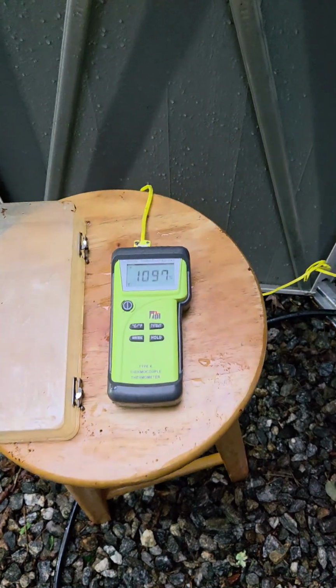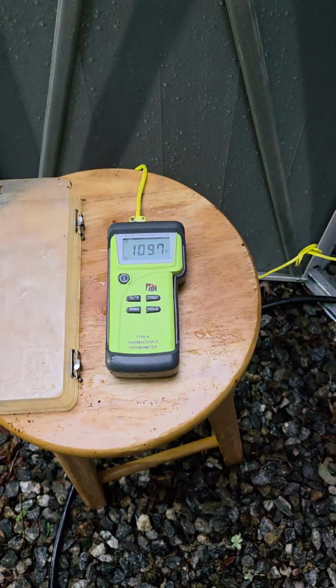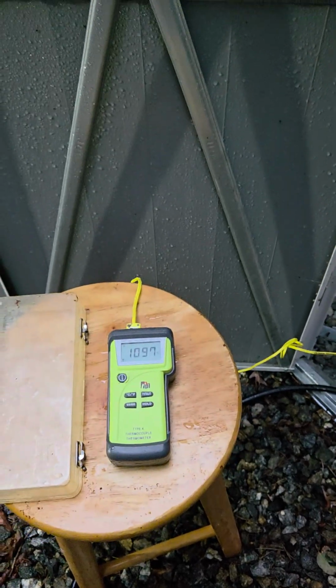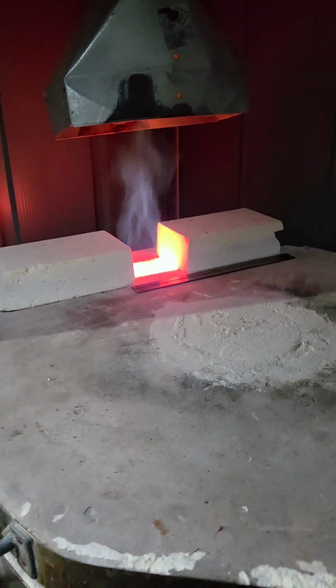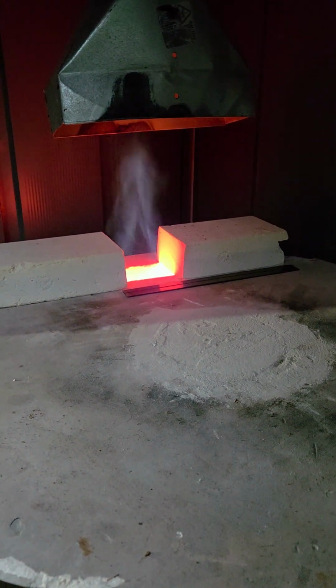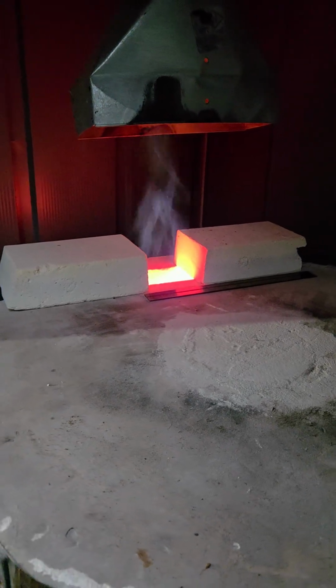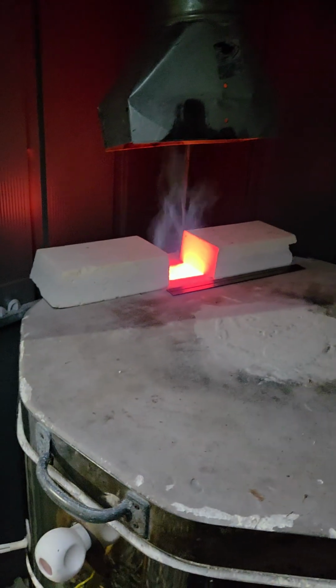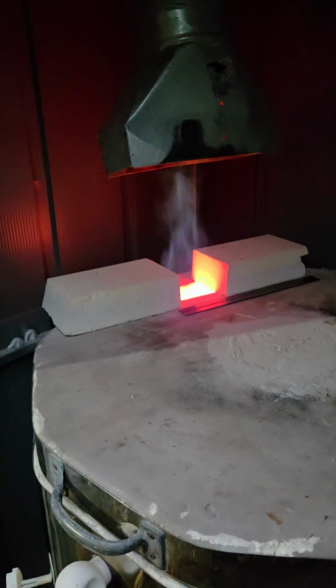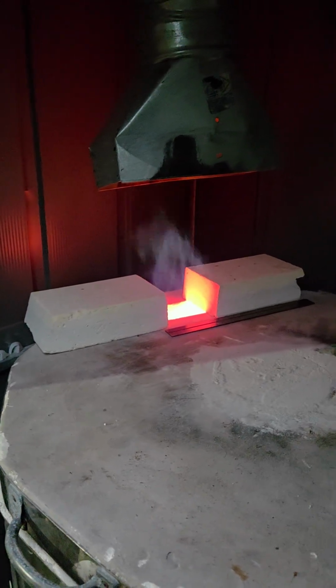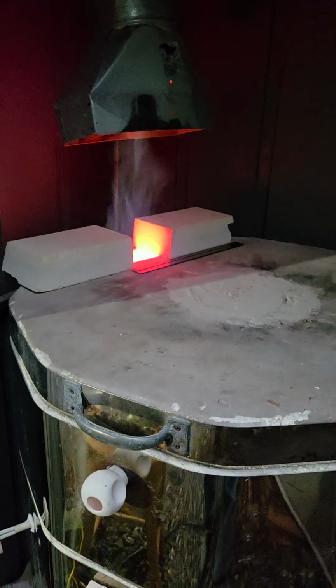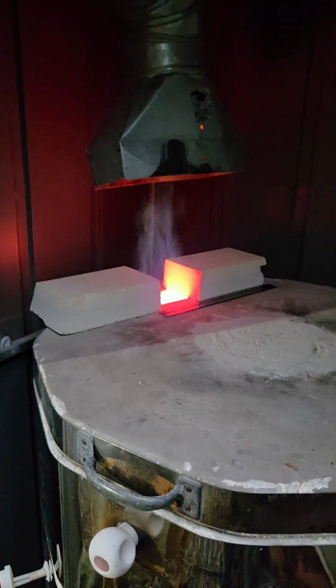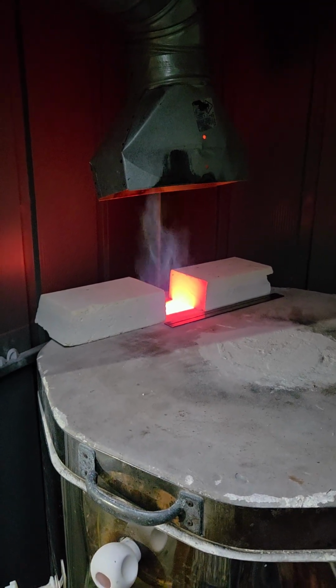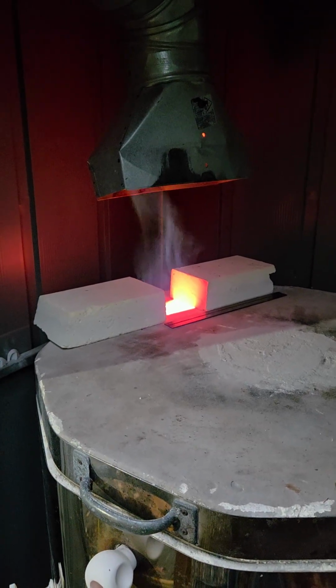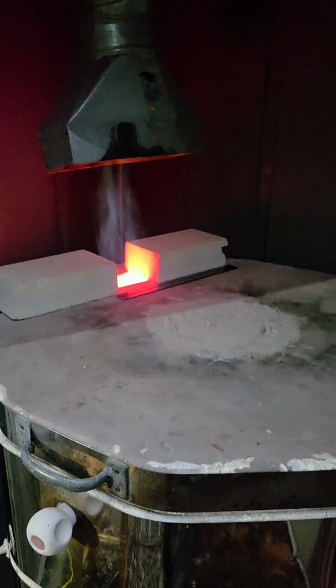So I have been doing timing tests starting at about 1,070 and then again at 1,090 degrees. And at the current settings, which I found is actually not 3.5, it's about 3 5/8, maybe slightly larger, the kiln has finally slowed down to about 108 degrees centigrade climb per hour. And I like to keep it at least 150 at this point, but usually between around 1050, 1060, and 1090, I usually have to go ahead and increase it. So what I'm going to do is open it up to 4 inches and then do another timing test after it stabilizes and continue the climb.